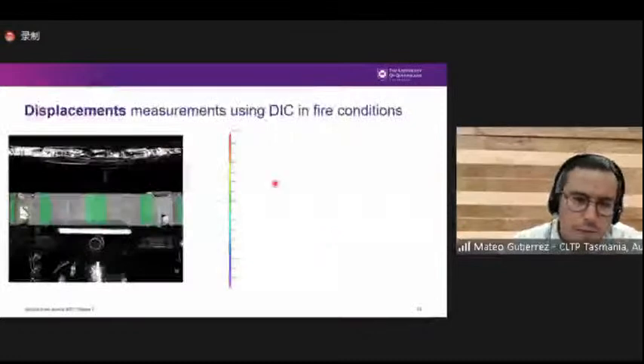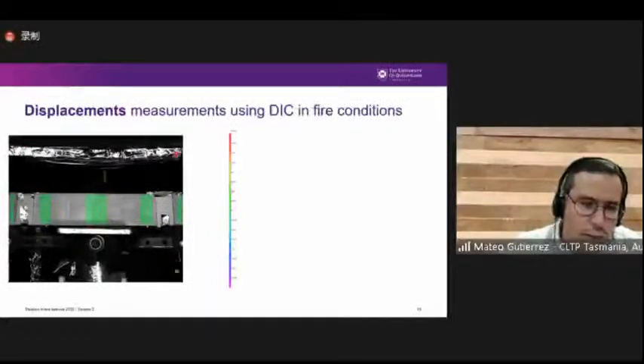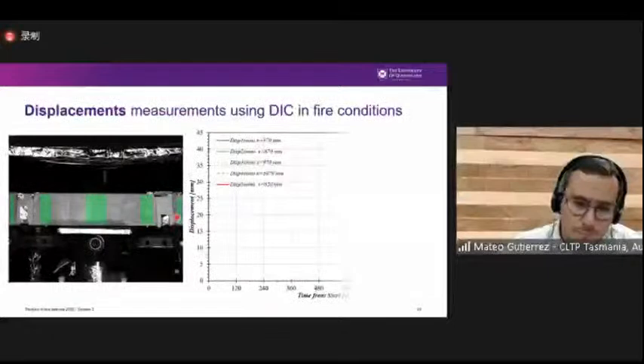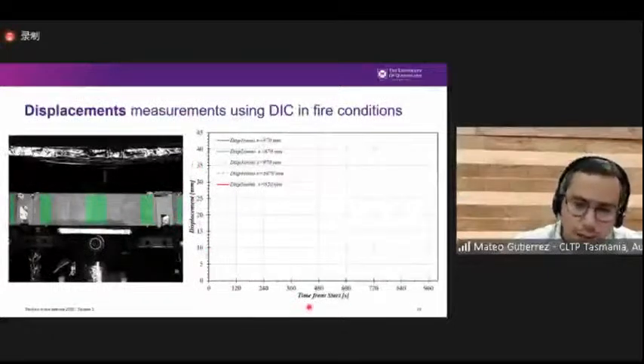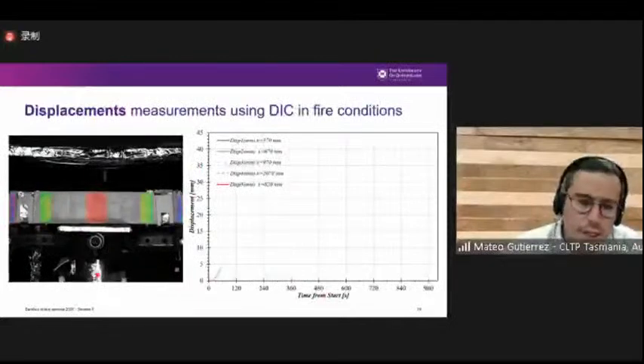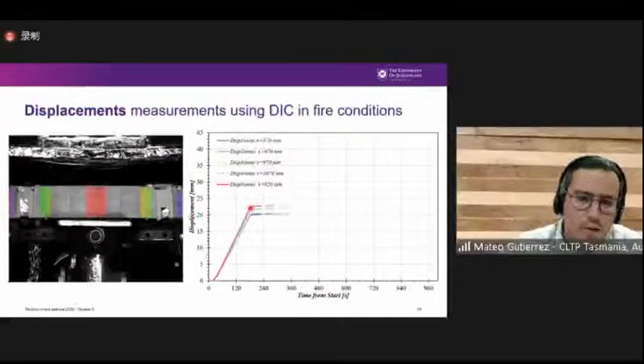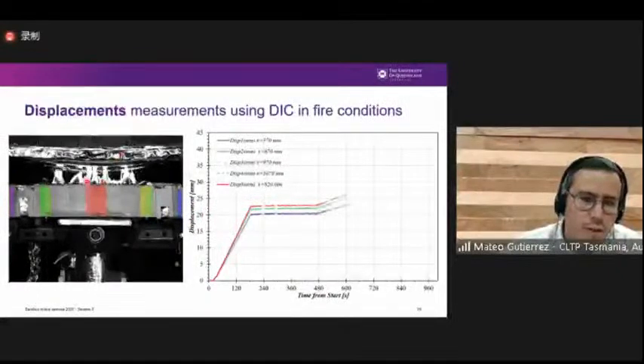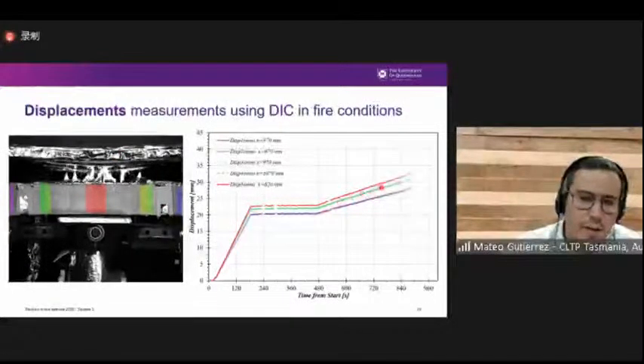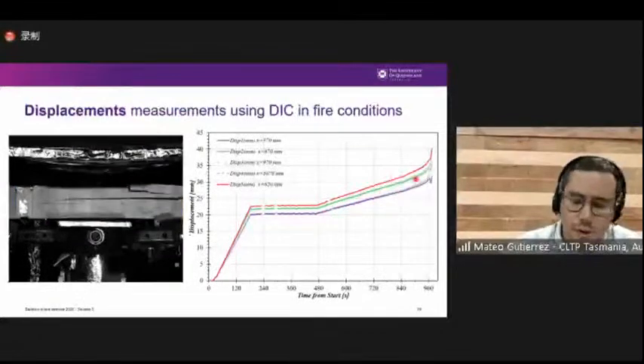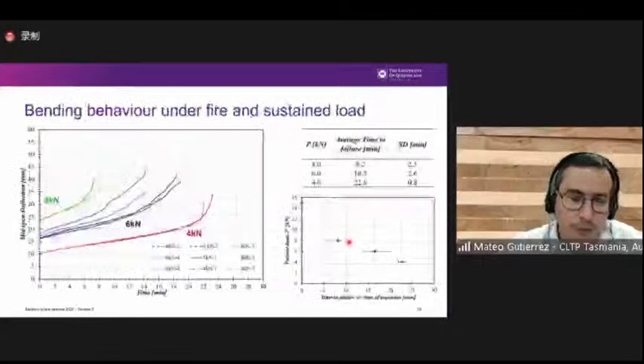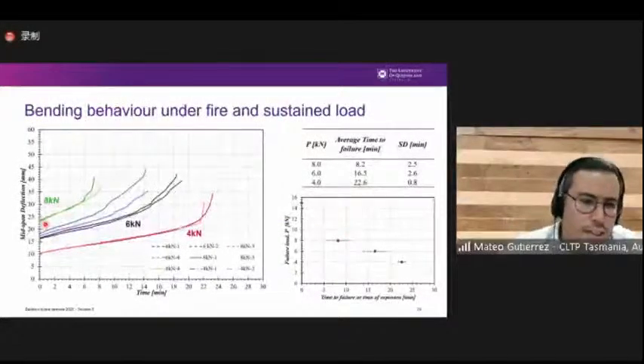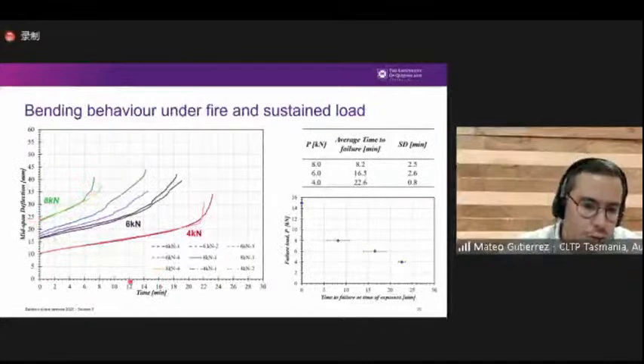So if you look at this video here, you will see that, again, this is a digital image correlation analysis where you will see the deflections in the central third of the beam. So here you have displacement against time, right? What you will see here is that we loaded the beam until we reach the target load. Then we start applying the fire exposure. Once you have the fire, the beam starts having more and more deflections until it finally reaches the failure, right? Thanks to the use of this DIC, or digital image correlation, we obtain the deflections against time of exposure for all our beams.